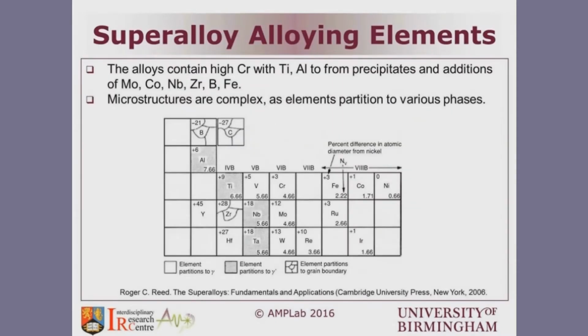But nickel superalloys are rather complex. They basically contain more than 10 alloying elements in some cases, and can be even more complex beyond that. They contain elements like chromium, used to improve their oxidation resistance, as well as elements like titanium and aluminium that form precipitates to strengthen them, in addition to other alloying elements like molybdenum, cobalt, niobium, zirconium, boron, and iron. These different alloying elements have various roles in the nickel superalloys achieving their properties.